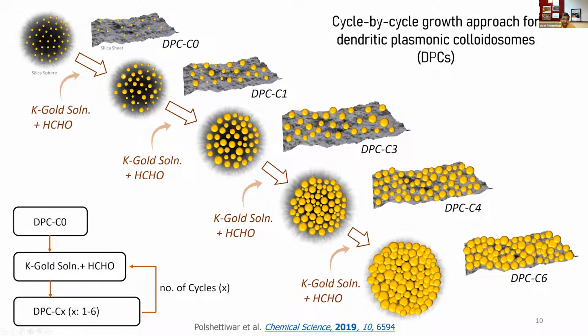And then in the second step, you control the nucleation and growth in such a way that you only grow the existing gold nanoparticles without creating new gold nanoparticles. That way, at every cycle I keep increasing the size of the gold nanoparticles, and you can see now the gaps between the gold nanoparticles are decreasing. That's what we wanted. We wanted to tune the gaps between the gold nanoparticles. Obviously, theoretically, they will all grow at similar kinetics, but in reality, they will not, because silica is heterogeneous.